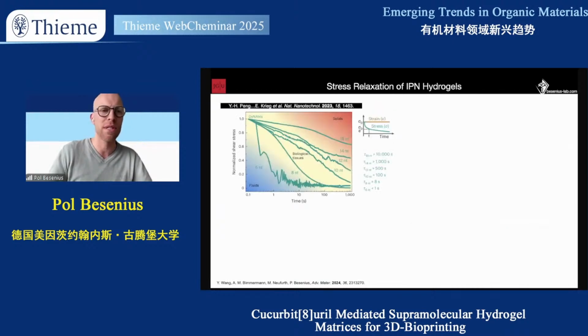And this has consequences that are very important. The reason they're important, and that I've shown on the graph here, is in terms of network dynamics. So typically the rheologists would talk about shear stress or stress relaxation, so the time it takes for a material to relax back to its original state when you apply strain. And I'd just like to highlight the beautiful work of Elisha Krieg in Dresden, who worked on DNA hydrogel materials, who published this beautiful Nature Nanotechnology paper a while ago, where the idea was that if you compare biological tissues in this viscoelastic regime, you can really go from a material that is more fluid-like to one that is more solid-like if you play around with the dynamics of the network. So it's not the degree of functionalization, degree of cross-linking, it's the dynamics that dominate the network properties.